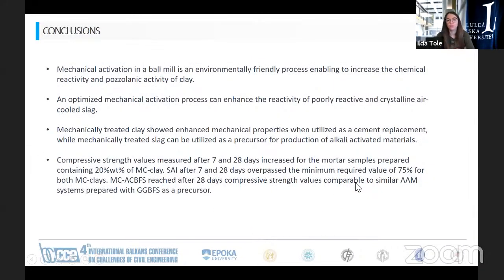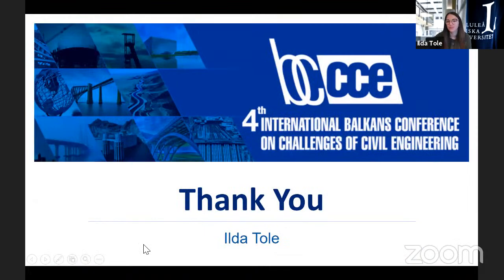So, as the conclusions, we could really state that mechanical activation in a ball mill is an environmentally friendly process, which is able to increase the chemical reactivity and the pozzolanic activity of clay, and can also increase the reactivity of poorly reactive crystalline air-cooled blast furnace slag. Normally, it is necessary to optimize the process parameters, especially for the air-cooled blast furnace slag. So thank you very much, and I'm here to welcome any questions from you.